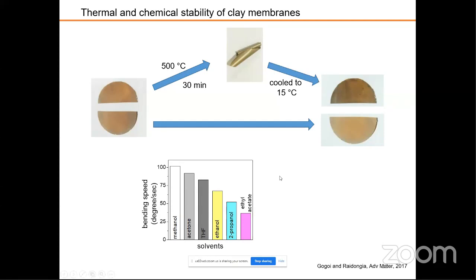So what we have shown here is that we can make a bilayer membrane and cut it into two pieces. One piece we have heated at 500 degrees centigrade. Then again it cools down, it becomes the same. After heating at 500 degrees centigrade, the property did not change. You can see the bending speed at different solvent vapors is the same. It was not affected by heating. So this material is very, very stable even after heating at very high temperature.